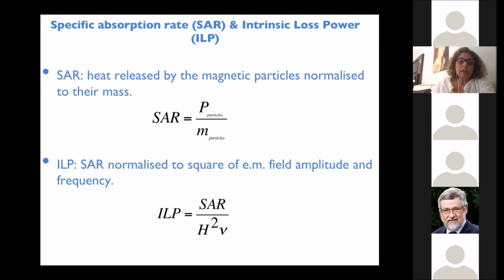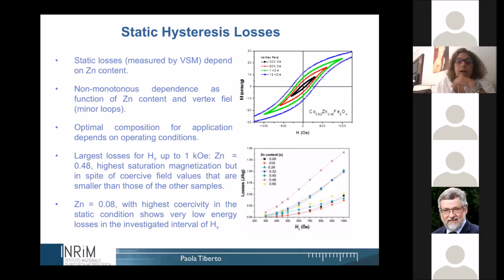Another important parameter is the intrinsic loss power, that is the SAR over the frequency at which the measurement is made and the applied magnetic field. Here are the results of our measurements. This is one composition, and as can be guessed, by increasing the magnetic field the area of the hysteresis loop is higher.